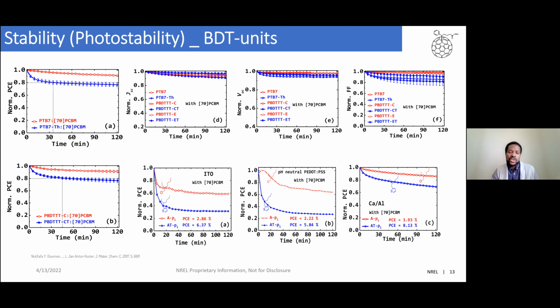So first, what we did is to make devices without PEDOT:PSS, just on the bare ITO. As you can see, the efficiency reduces, but the trend still remains. Similar with PEDOT:PSS, which is known to be acidic in the community. So we try to use pH neutral PEDOT:PSS. And here you can also see that the trend still remains.